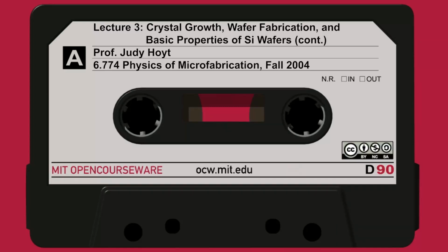If you wanted to know it in detail, you can probably break it out into different origins of vacancies and interstitials, but we don't take into account in any of these equations the actual mechanism by which they're formed. So when we wrote down this equation right here, we lumped all the different processes into a single activation energy. Whether it's a surface process, again, this is an equilibrium, or a bulk process by Frenkel pair by which it was created, this equation doesn't tell you. It's probably the sum of a lot of different processes. So it's an approximation.